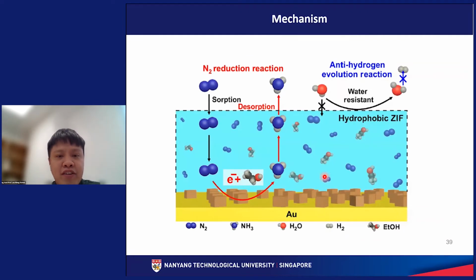So this is the mechanism of our study, whereby nitrogen can be absorbed into our hydrophobic MOF and subsequently react with electron and ethanol to form ammonia. So this ammonia can be dissolved from our system and subsequently characterized or quantified using the indophenol blue method. The MOF also serves as a hydrophobic barrier, whereby it prevents the access of water to our embedded electrocatalyst. If water cannot access, then we will be effectively inhibiting the hydrogen evolution reaction.